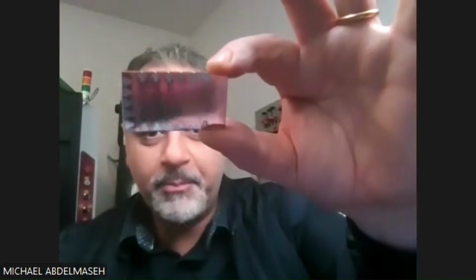The first one is to basically embed a copper tab inside the crystal while it's being grown. So basically, the crystal is being grown around a copper tab, and this is how you get your connection. It's embedded in molten metal, grown as a crystal, rather than just having a piece of copper being soldered on it. Solder is a very low melting alloy, and once the module is exposed to cycles of heating and cooling, it starts to crack and just disintegrates, and the module becomes useless. So I think in that regard, our modules are superior to anything available in the market, having these embedded connectors or embedded tabs already inside the crystal.